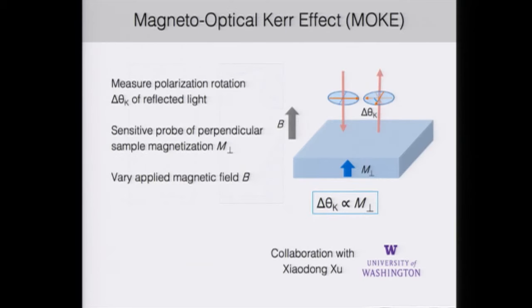So the first technique that we use to study 2D magnetism is the magneto-optical Kerr effect, or MOKE, which we performed in collaboration with Xiaodong Xu's group at the University of Washington. So the basic setup for MOKE is you take your sample, which has presumably an out-of-plane magnetization, and you shine in linearly polarized light normal to the surface. You then want to collect the signal of the reflected light, which will have a rotation in the linear polarization called the Kerr rotation. And this Kerr rotation is a very sensitive probe of the perpendicular magnetization. So it's just linearly proportional to your magnetic signal. And you can apply an out-of-plane magnetic field to change the magnetization in your sample and then track how the Kerr rotation responds.